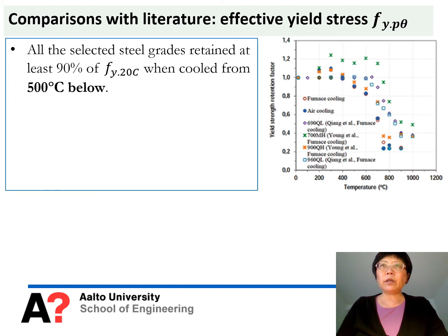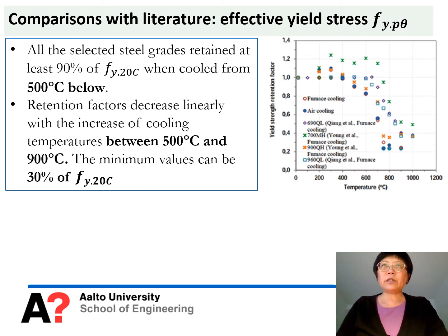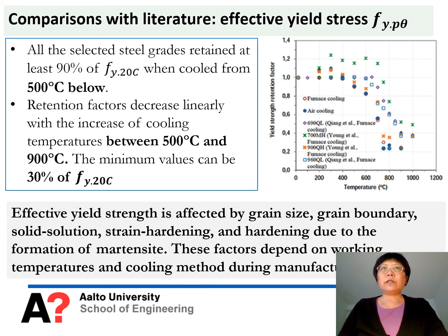So basically it can be seen here that when the steel is cooled from 500 and below, the retention is about 90% of the room temperature value. But after that, the retention factor decreased linearly with the increase of cooling temperature, and the minimum value can be about 30% of the room temperature value. The reason is that the effective yield strength is affected by grain size, grain boundary, solid solution, strain hardening, and hardening due to the formation of martensite. These factors actually depend on working condition, working temperature, and cooling method during the manufacturing process.